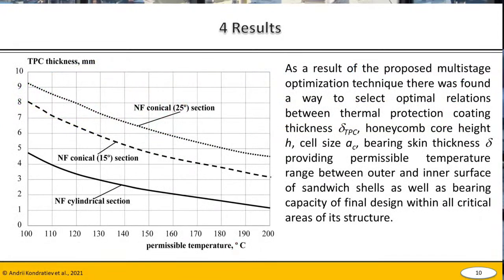As a result of the proposed multi-stage optimization technique, there was found a way to select the optimal relations between thickness of the thermal protection coating, height and cell size of the honeycomb core, and thickness of bearing skins.